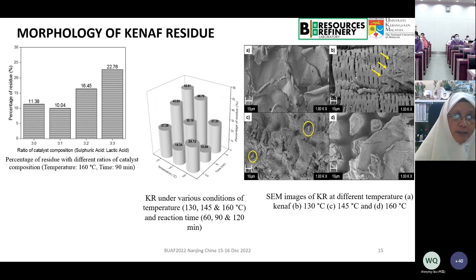Okay, so we are using a catalyst. Before this, we just used sulfuric acid, but now we make a combination of sulfuric acid and lactic acid, not to make it so vigorous, but to control the reaction. With that, we can have about 10% as far as yield is concerned. You will see that lots of the lignin area has been delignified, and some cellulose has been degraded and dissolved in the liquefaction solvent, giving you the residue here.